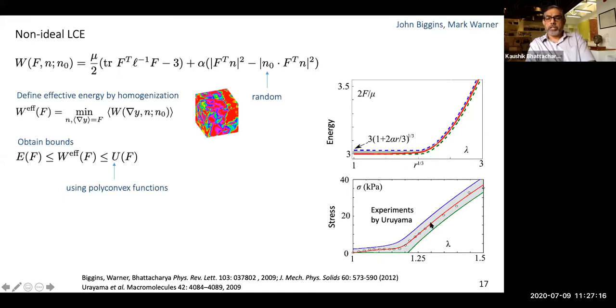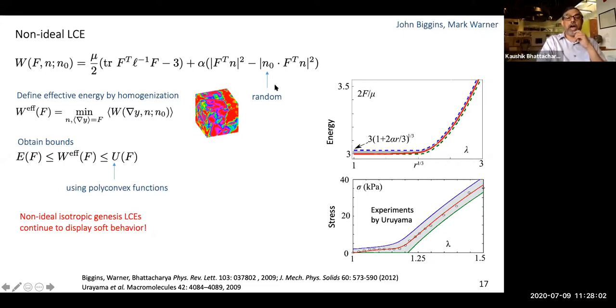And in fact, these are the experiments. You can compute the bounds and use the fact that the stress-stretch relation has to be monotone and obtain bounds on the stress-strain behavior. And that's the theoretical bounds. And then the circles are actually the experiments. So you can see that the bounds are tight and show you that you still have soft behavior. The red line is the result of some simulation, and you see that it does very well.